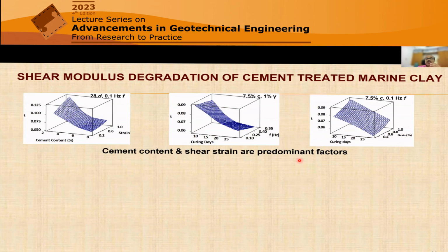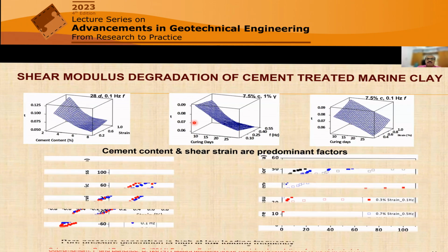So we have done 3D plots, and we have seen that factors like frequency, curing stress, curing days, cement content and the strain are the obviously predominant factors. And that's what we expected as well. But before going further, there is an interesting feature. At the lower cement content, the degradation is very obvious, but at the higher cement content, degradation is of course reduced, but it is also a function of the frequency of loading. How frequency of loading plays a role, that we studied.